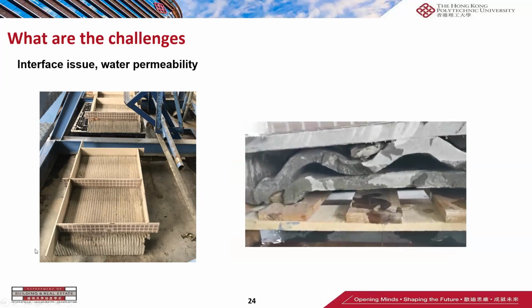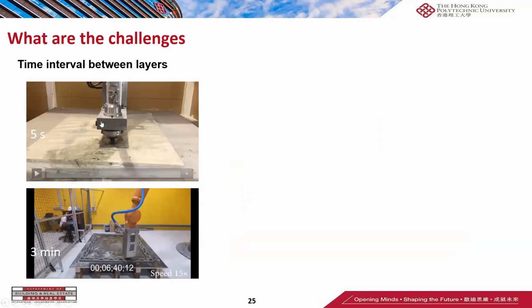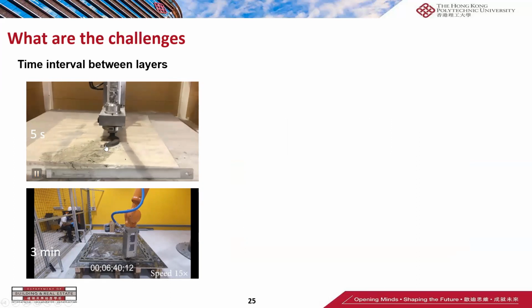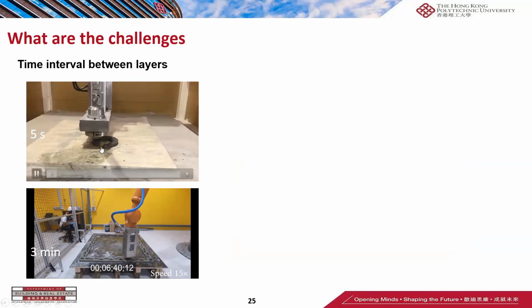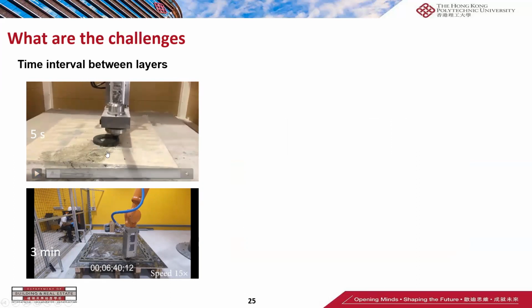Then why will the interface be weak? So let's go to this. The weak interface is mainly caused by the time interval between layers. For example, when we print a small structure by 3D concrete printing, it will start from this point. This is the starting point. Then for the small structure, it will take around 5 seconds to reach the same point in the second layer. Then the 5 seconds we define as the time interval between layers.